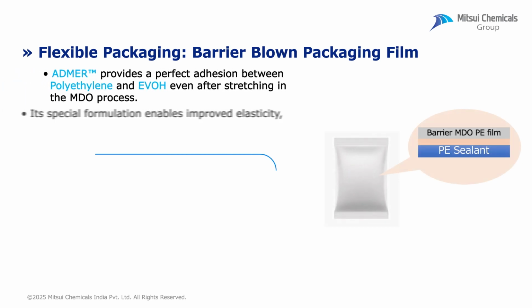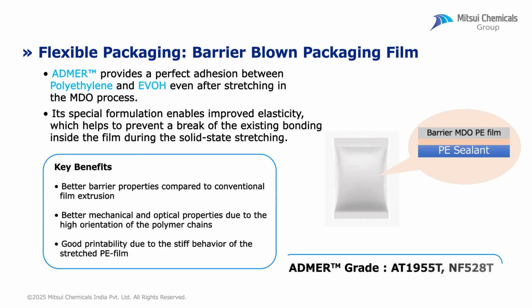Due to stiffer polyethylene based Admer grades, it sustains stretching in the MDO direction and hence contributes to better mechanical and optical properties in the final film. Admer is well established for EVOH based MDO PE film. Certain concentrate grades are also available as per the requirement.